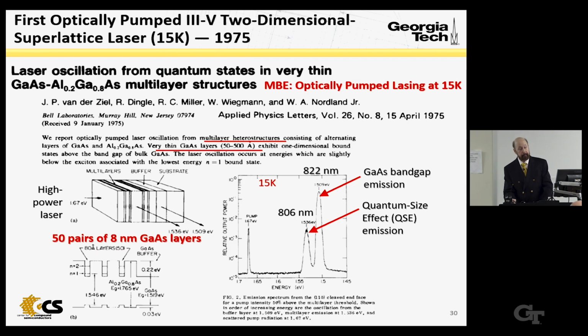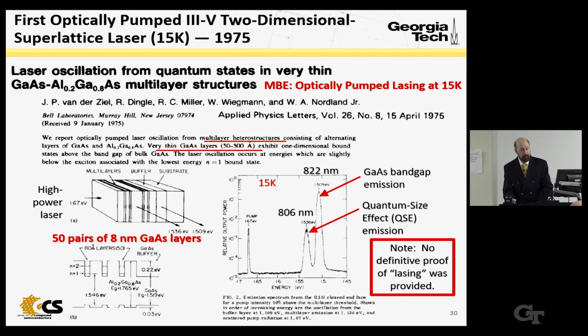I want to point out, if you look carefully at this paper, you'll see there is no definitive proof of lasing, even though they claimed, as in the title, laser oscillation. They might have had stimulated emission, but even that wasn't proven by their data. So I'm still skeptical about this, and unfortunately, all those people are dead. So you can't ask them. At any rate, the point was that we have an exciting new concept of a laser with ultra-thin quantum well, multi-quantum well, multiple thin layer active regions. And at this time, MBE was, if you will, the premier technology for these kinds of thin layers.